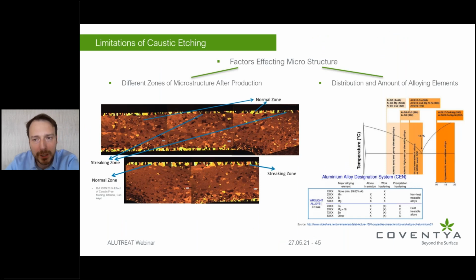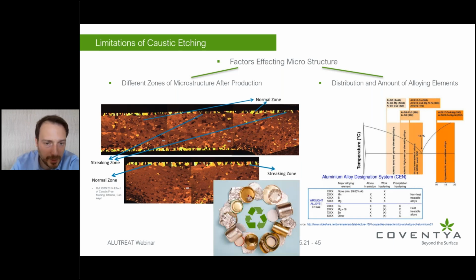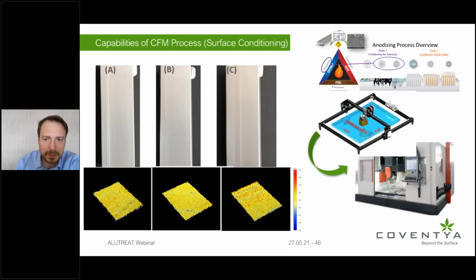Therefore, we like to use more compact and more flexible processes like we have introduced, especially if we are thinking about not only the extrusion process or the forging process changing and making the microstructure much more inhomogeneous, but also the alloying elements, meaning different series of aluminum, and the use of, which is a hot topic today, recycled aluminum, which is increasing the silicon and iron content, will have an effect on the color.